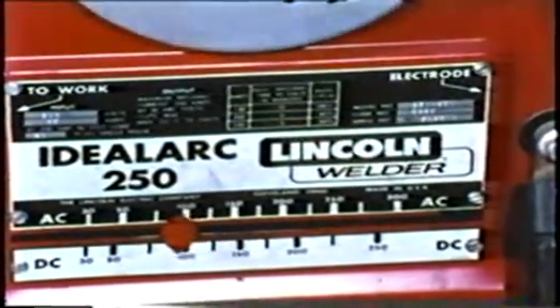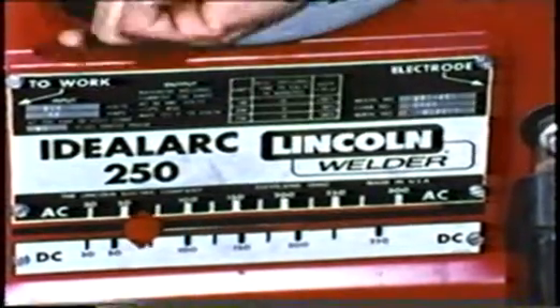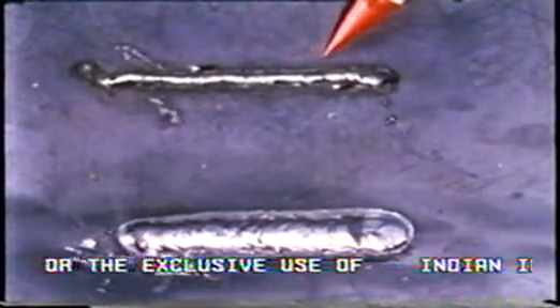If the current is set too low, there is not enough heat to melt the base metal and the molten pool will be too small. It will be difficult to strike and maintain the arc. A narrow bead with poor fusion is the result when the current is set too low, again as compared to a correctly made weld bead at proper current setting.